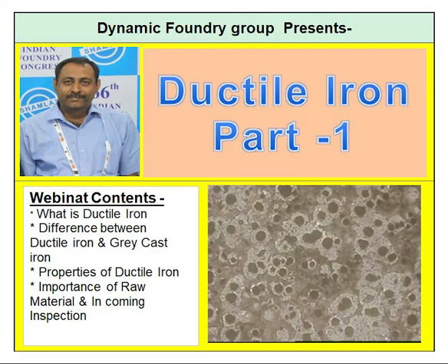Achieving ferritic grade in as-cast condition is a very big challenge, as we all know, because we have to control the cooling rate and we have to control the manganese. All the details we will see in the further slides also. It depends on many things. Number one, pearlite promoting elements like manganese and copper. These elements promote pearlite, and their presence will restrict ferritic structure and promote pearlitic structure. So we will not be able to get an as-cast ferritic matrix.